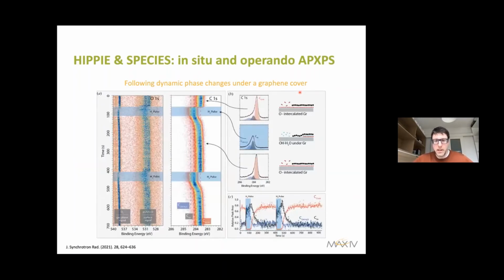And what we did, and what was done here, and you will hear this a lot in the remaining talk, was that the partial pressure, or the gas composition over the catalyst, was changed rapidly by pulsing of gases. In this particular case, the pulsing was done by switching the mass flow controllers, which can be done on the order of seconds to tenths of seconds. And this is seen in this graph.